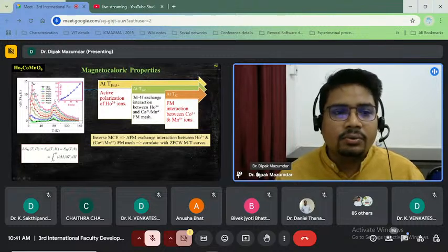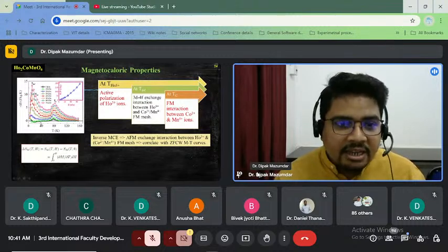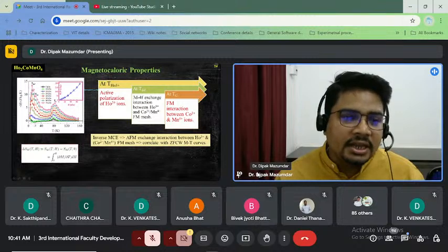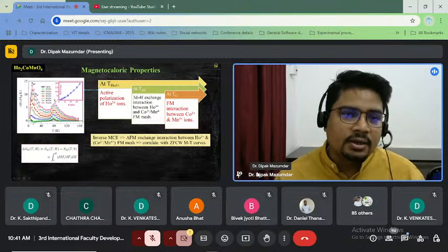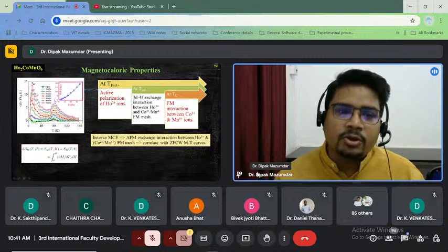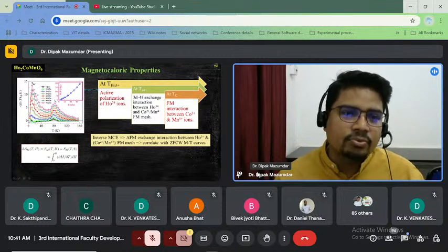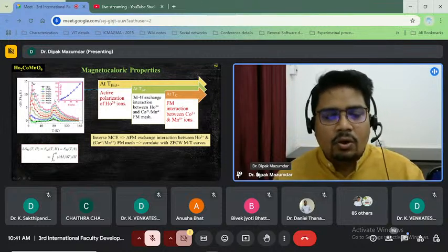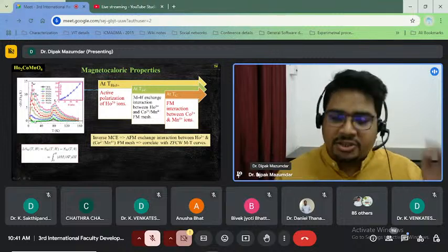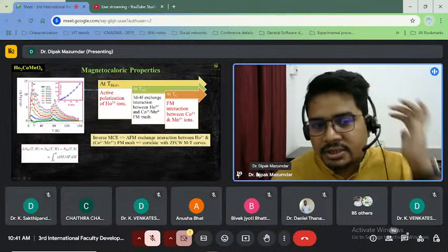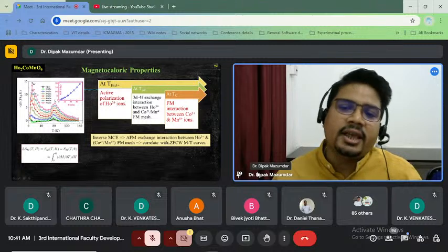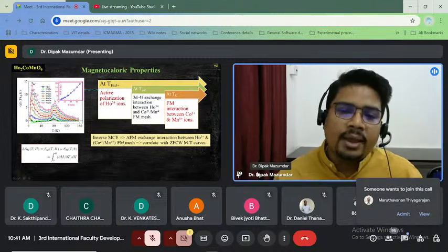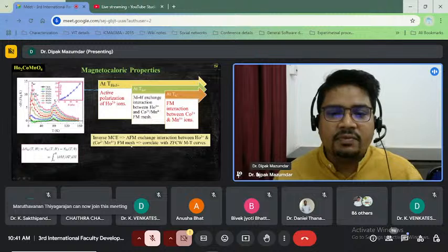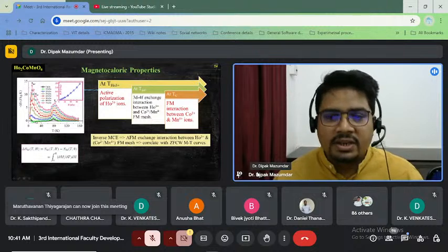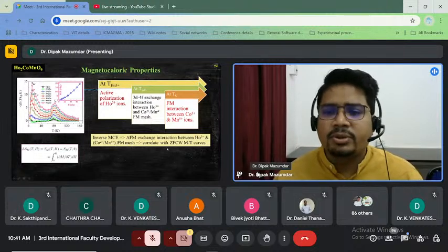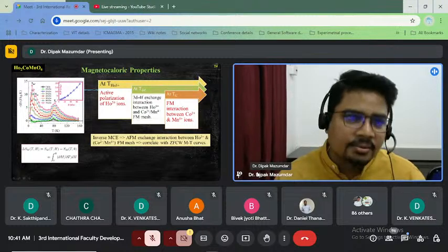Then after, we have observed some negative magnetocaloric data here, which is also known as the inverse magnetocaloric effect, and this is up to a 10 kOe field, which also resembles the magnetization data. So in this region, the antiferromagnetic exchange interaction between holmium and the transition metal ferromagnetic mesh is dominating at low field regions. So this data can also be correlated with our ZFC-FCW M-T curves.